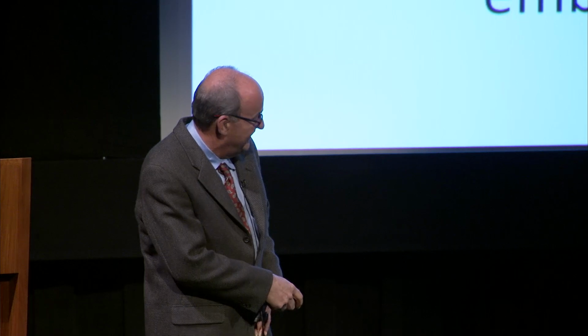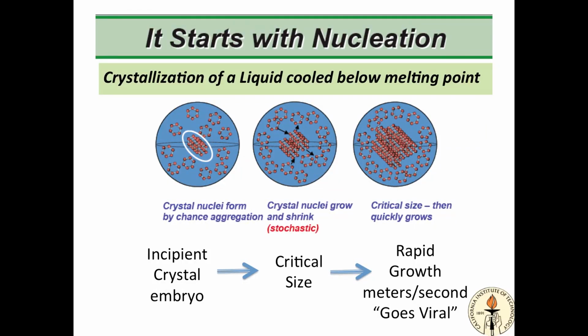Or you post a video on YouTube, and you get some views, and sometimes you get a few views, and then you get a few more views, and then if the mood is right, it goes viral, right? So there are these fluctuations in that random liquid mess, and crystals try to form. If they're too small, they're fighting against their neighbors that are in the wrong place. As you get more and more of them together and making a bigger crystal, they win the battle against their neighbors. They call that the nucleation barrier. And if you get over that nucleation barrier, if the nucleus of atoms gets to a critical size, then it takes off and it grows like crazy. Once it gets critical, it grows.